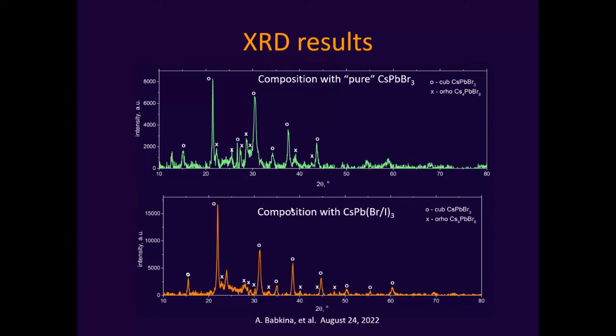The problem is that when we are dealing with perovskite crystals with the same crystal modification, their reflexes will be very close. And because we're dealing with very small crystals with sizes less than 10 nanometers, the reflexes are really very wide. You see, they are wide indeed, compared with monocrystals. That's why maybe these reflexes contain both bromide perovskite and iodide perovskite at the same time, but we cannot distinguish them separately. Maybe, or maybe not. So we're still in progress.